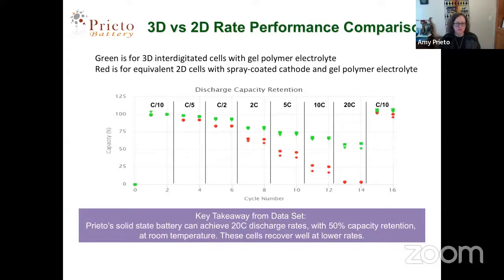What I'm showing you here is capacity in percentage. This is after the formation cycles. That's what we set as our 100% capacity, and then cycle number as a function of different rates going up to 20C, so full charge or discharge in 3 minutes. The green data is for the 3D interdigitated cells, and the red data is for the 2D cell.